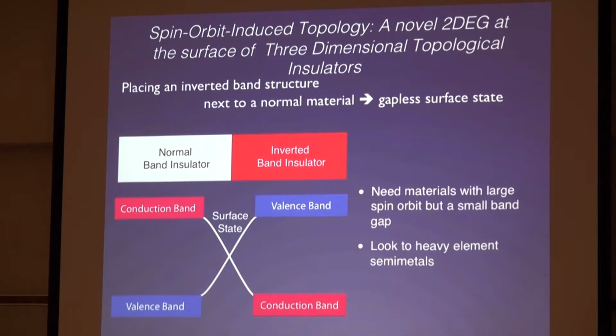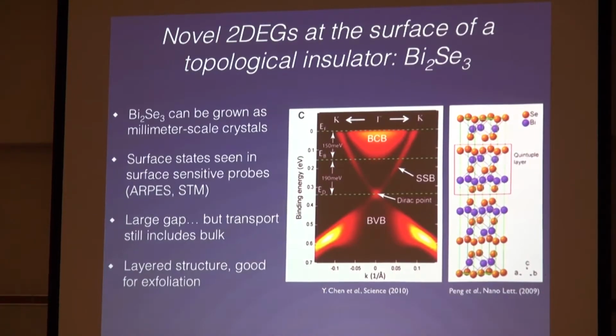But it's when we interface the system that really at its heart has a different topology than what I would call a normal band insulator like the vacuum. It's when you interface these two materials, you actually get an interesting surface state. This surface state has a Dirac-like linear band dispersion, and also has spin and momentum tied together. So it's interesting. But you need something that is a heavy element, so that has strong spin-orbit coupling, and also has a small band gap. And one of the material systems that this has arisen in is bismuth selenide and bismuth telluride. Very large, high-quality crystals of these can be grown. JP's grown these and some variation of these here at Maryland.